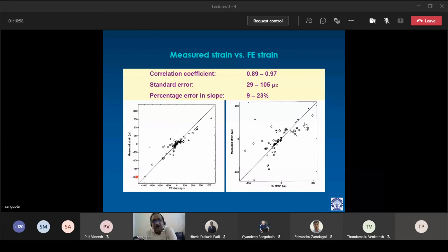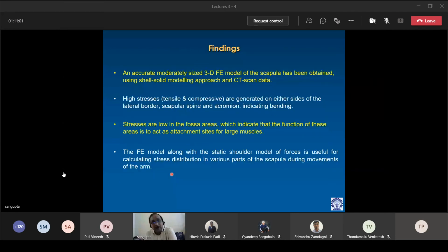Therefore, an accurate, moderately sized FE model of the scapula was obtained using a shell-solid modeling approach and CT scan data. High stresses, tensile as well as compressive, were generated on either side of the lateral border, scapular spine, and acromion, indicating bending of the structure. The stresses were low in the fossa area, as you have seen in the picture, which indicates that the function of these areas is to act as attachment sites of large muscles, as I told you, rather than transfer of loads. So the FE model, along with the static shoulder model of forces, is useful for calculating stress distribution in various parts of the scapula during specific movements of the arm.